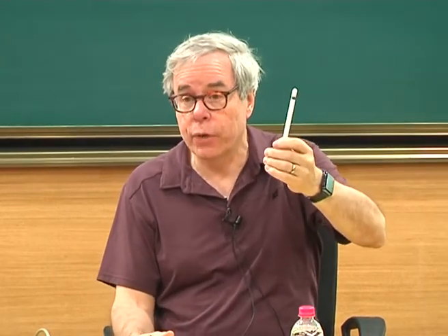The important thing about this model that I want to make sure everyone understands is that I'm changing the degree of order by just swapping atoms on a sublattice, right? I'm not changing alloy composition. I'm just swapping atoms on a sublattice. And so this model, I've put this in terms of a Bragg-Williams model, but it's precisely the same model for magnetic ordering, where you have spins up and spin down. So you can just change the degree of magnetic order by just flipping spins, right? There's no overall conservation law involved here. It's just flipping spins.